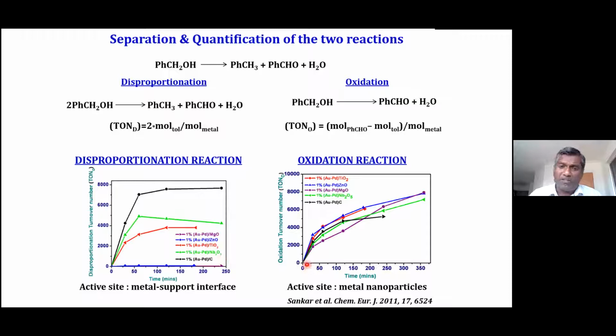And if we plot for all the 5 catalysts, the turnover number for the oxidation reaction is almost the same. But for the disproportionation reaction, you can see there is no disproportionation for zinc oxide and magnesium oxide, and carbon supported catalysts catalyze these reactions very effectively.